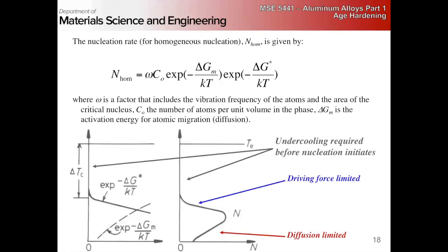Right? And so one last thing we have to look at is the nucleation rate. Right? So we have Arrhenius terms. This is the nucleation rate, right? This is a factor that includes the vibration frequency and the area of the critical nucleus, right? Now we have two terms. One that is the activation energy for nucleation, right? This is delta G star, so this is the activation barrier we have to overcome to create a nucleus of the critical radius, right? And then this Arrhenius term is the diffusion term, right? It's the activation energy for atomic migration.